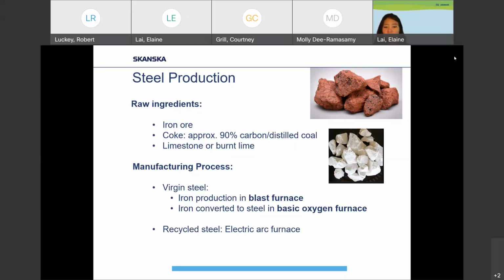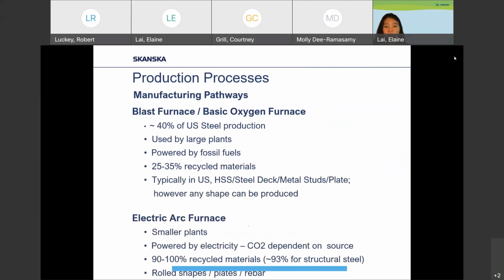Recycled steel, this is also very common, but this is produced in a different type of furnace that they call the electric arc furnace, or EAF for short. Why these production and manufacturing pathways matter is that the pathway that you choose entirely drives the carbon intensity of that steel. It's inherent differences in the production processes at play that directly impact and determine the carbon intensity of the final steel product.